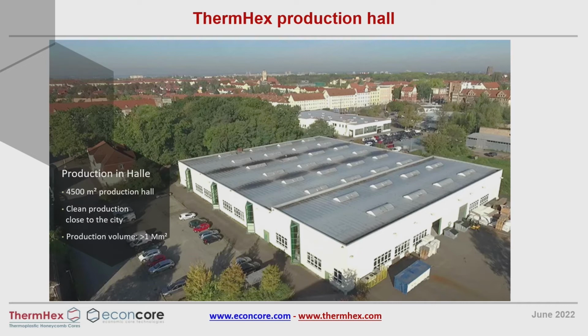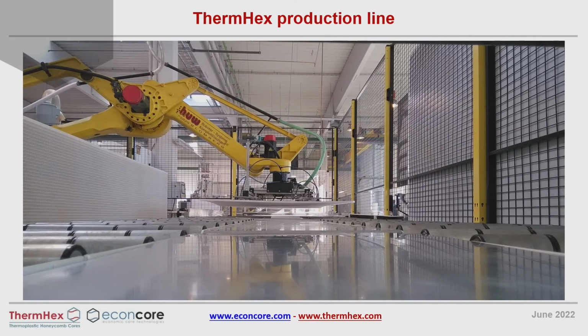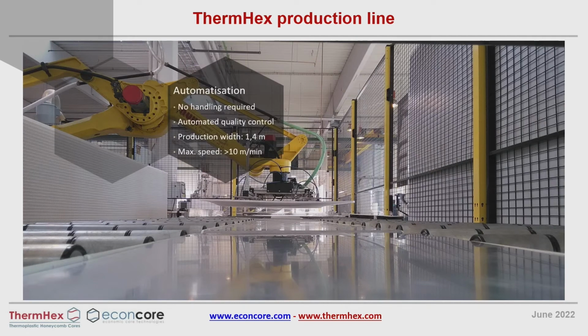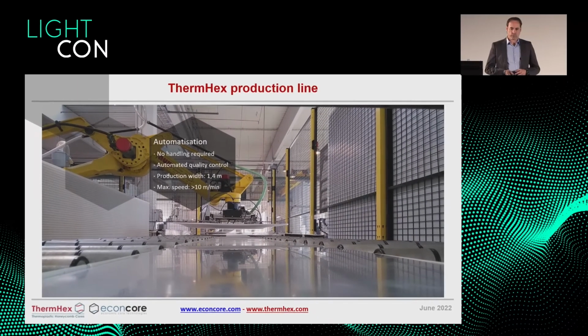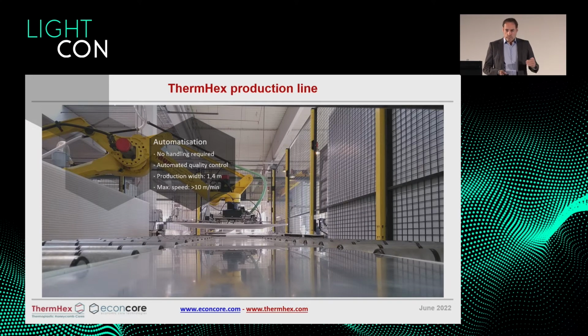So this is our location in Halle, about 5,000 square meters, very close to the city because it's very environmental friendly, clean processing of thermoplastics. And we last year produced about 1 million square meters of honeycomb cores. So a very automated production, maximum production width 1.4 meter, standard is 1.2. We have very automated production quality control and maximum speed of more than 10 meters per minute.